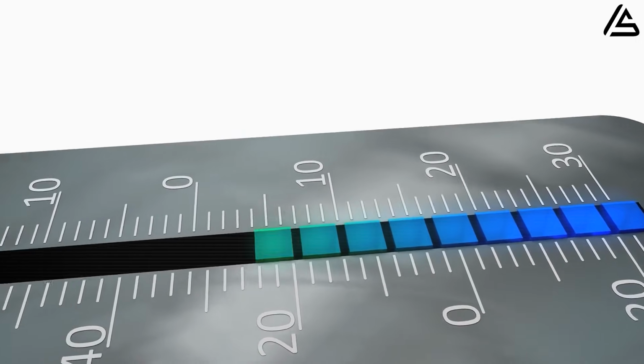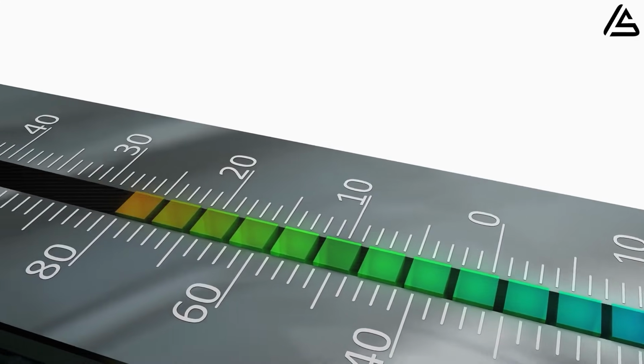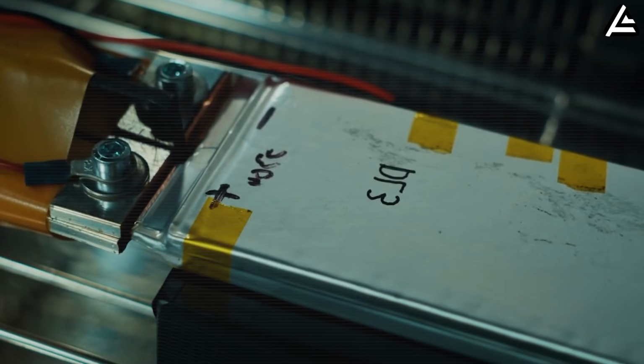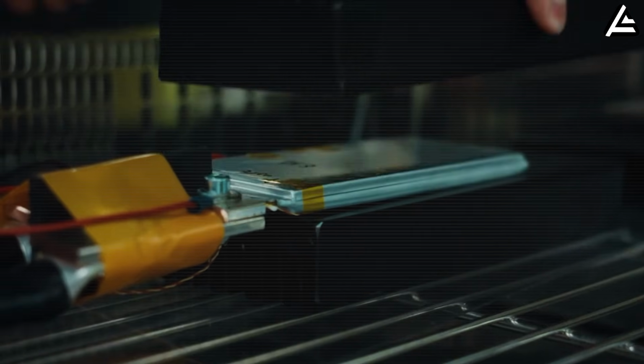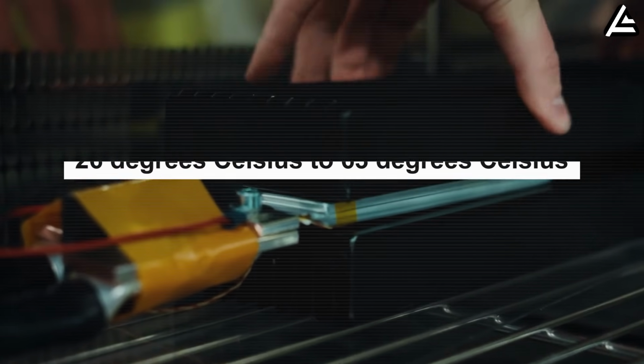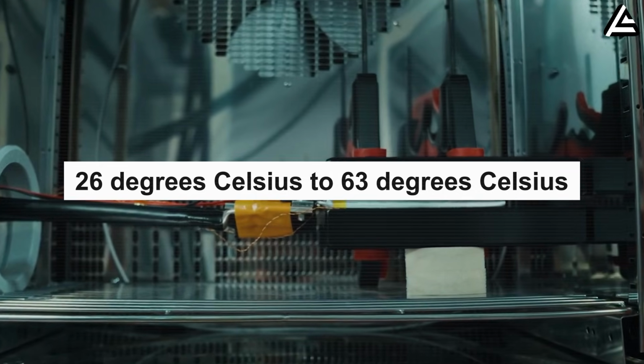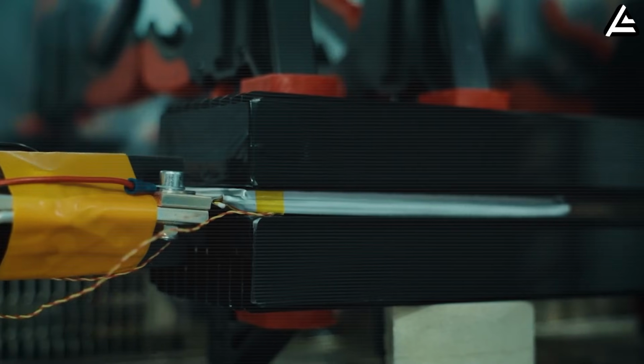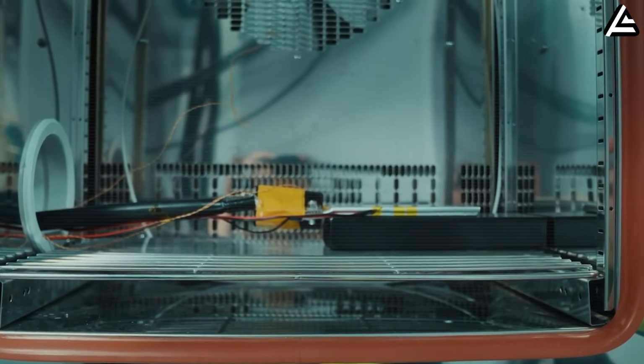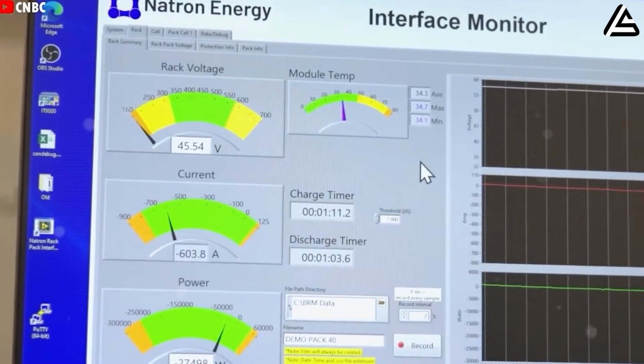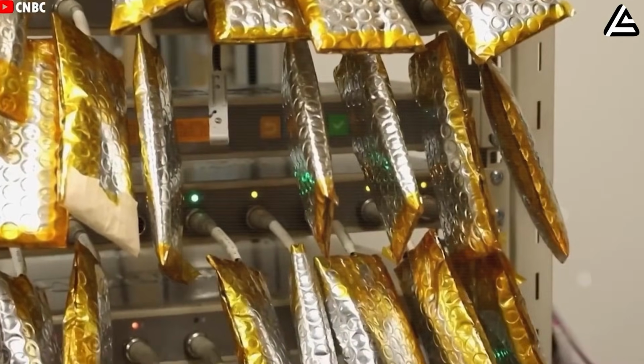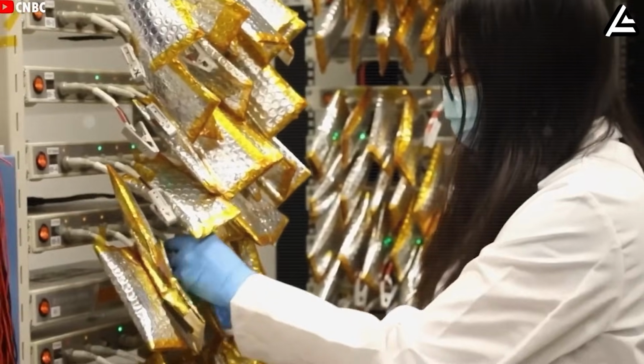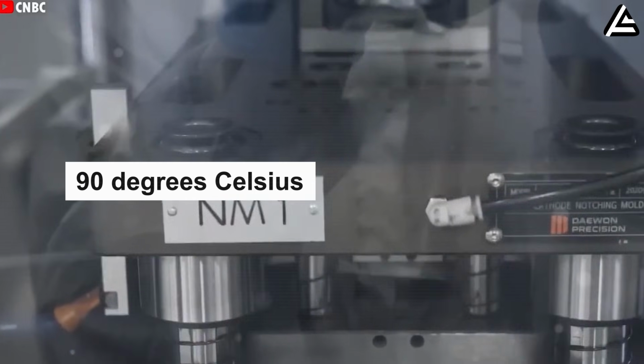But alongside that speed came another number that triggered debate: temperature. During the test, the surface temperature of the single cell rose from about 26 degrees Celsius to 63 degrees Celsius when using 2 heat sinks. With only one heat sink and more limited passive cooling, the temperature climbed further, eventually reaching 90 degrees Celsius.